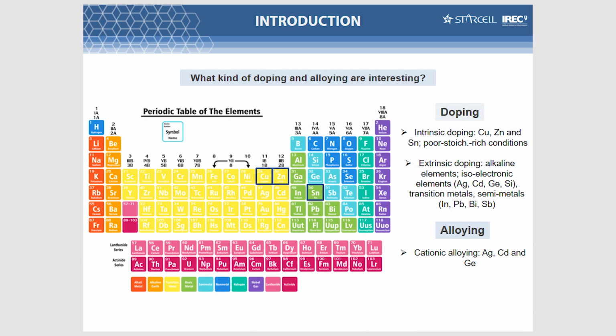Then if we consider the structure of kesterite that is formed by copper, zinc and tin, then we can have an idea what kind of alloying and doping is required for these materials. And in principle, with doping, of course, we can have intrinsic doping, so we have to play with the same structure, modifying copper, zinc and tin and see what happens, and if we can win something. We can have extrinsic doping, and learning from CIGS, of course, alkaline doping can be relevant, but also it will be very important to study isoelectronic doping, like with silver, cadmium, germanium, silicon, or even with other materials like indium, lead, bismuth, and antimony. And for alloying, of course, cationic alloying can be very relevant as well, and the most important one probably is the substitution of copper by silver, zinc by cadmium, and tin by germanium.